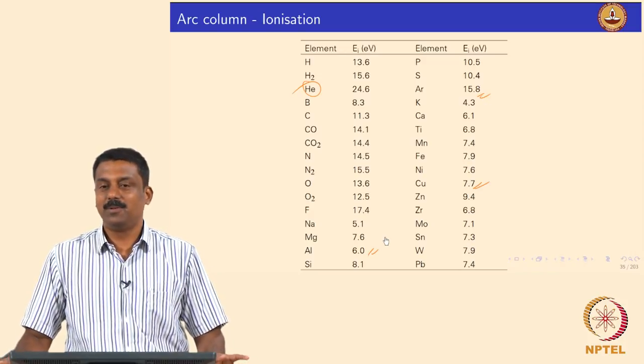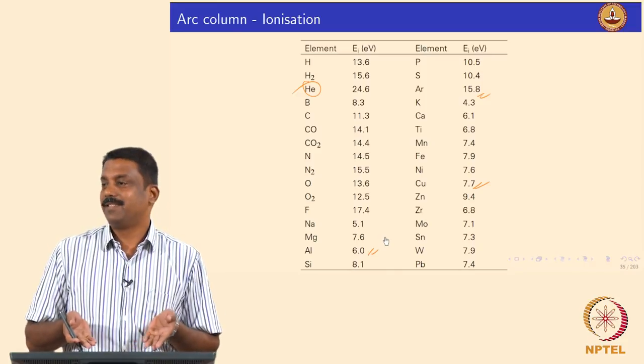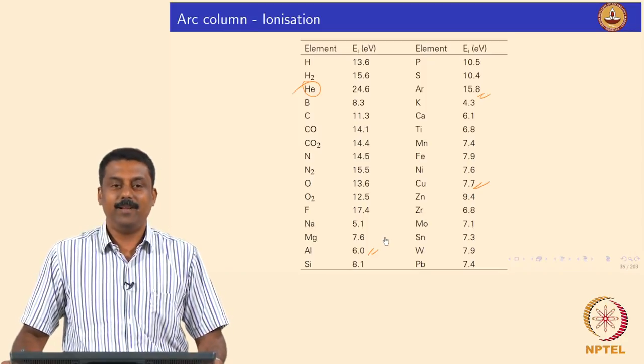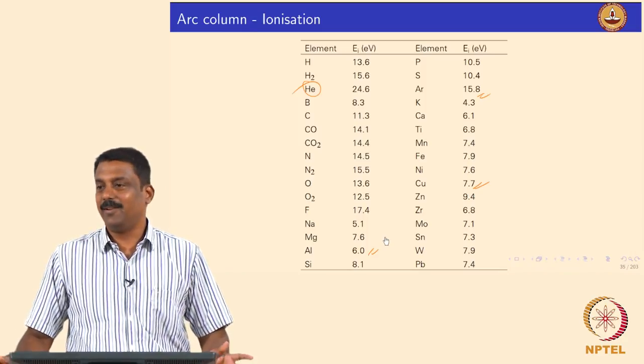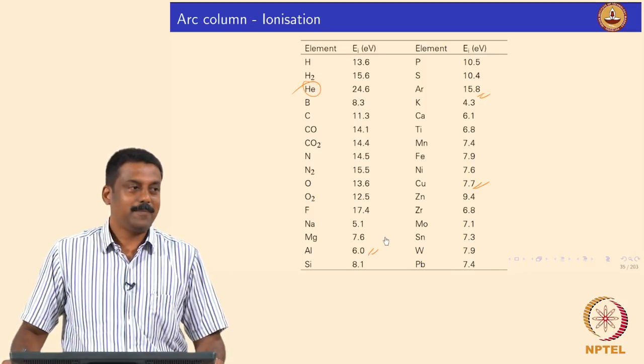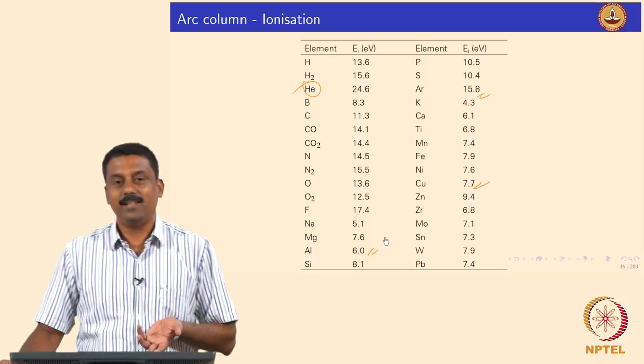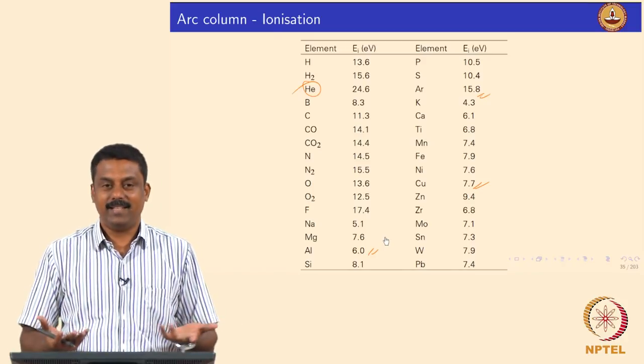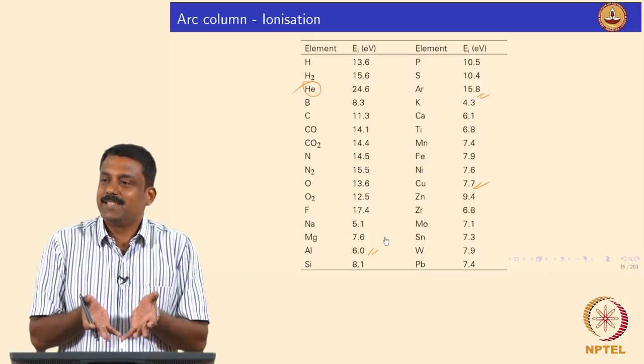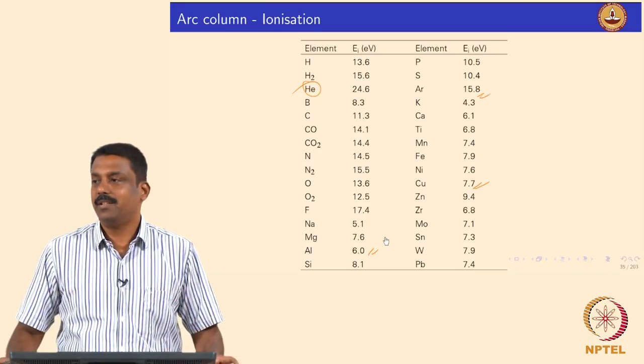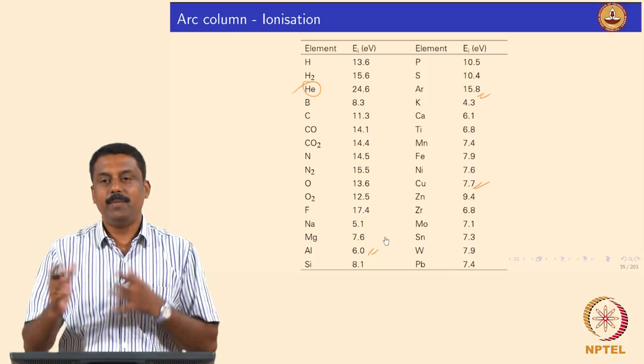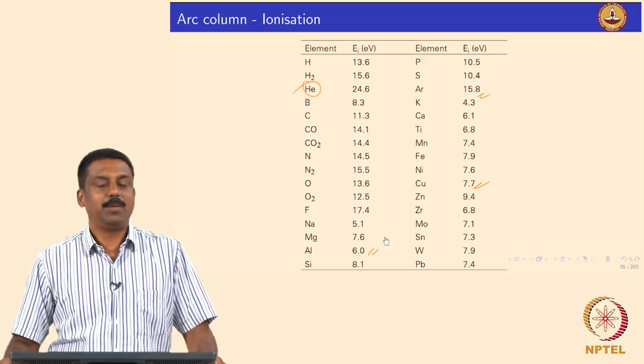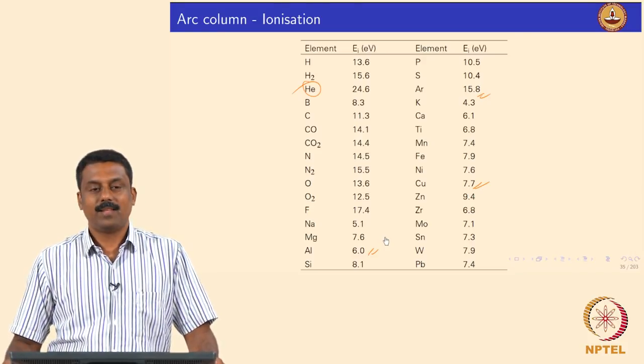So the fundamentals of choosing a shielding gas are derived from this physics. It is not like you can randomly go and weld with argon or helium — the arc temperature is determined by the ionization energy of the gas. The principles of choosing a shielding gas are all determined by the physics governing sustained discharge. Similarly, if you mix two gases, that will also affect the arc temperature because the ionization will be changed.